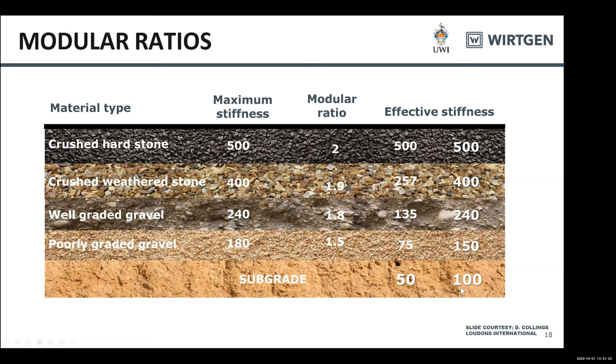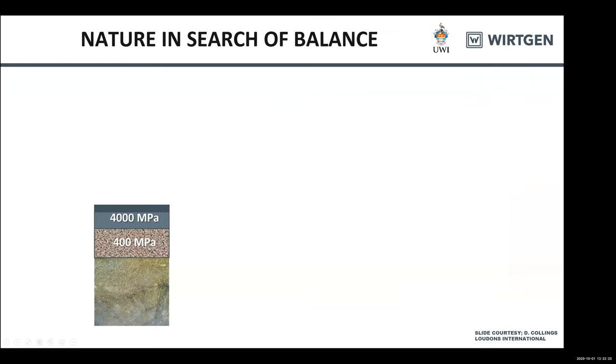As we can see, there is a difference between the maximum stiffness and the effective stiffness. When we do the calculation, due to the modular ratio, which is shown here, this is the maximum modular ratio allowed between these two materials. We see that in this case, the effective stiffness that is actually in the pavement is below the maximum stiffness that material can achieve. But if nature changes the subgrade condition, so that we have a poorer subgrade with a lower effective stiffness or modulus, we see that the impact is quite impressive. Up to here, none of the maximum stiffness values can be achieved. So, what does this do to us